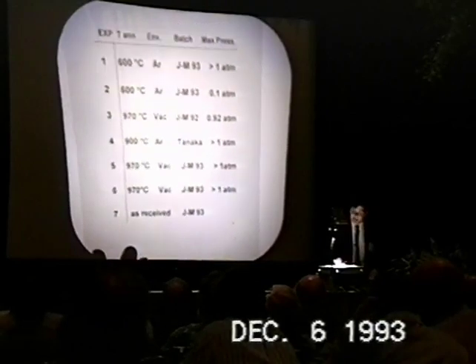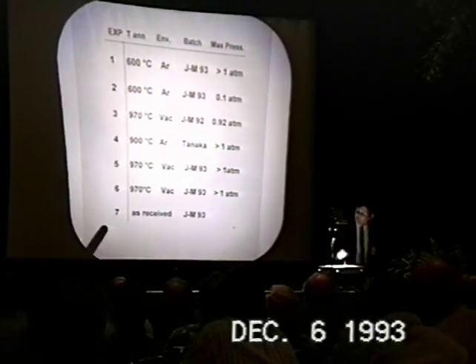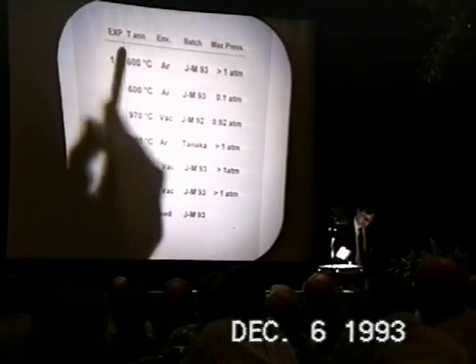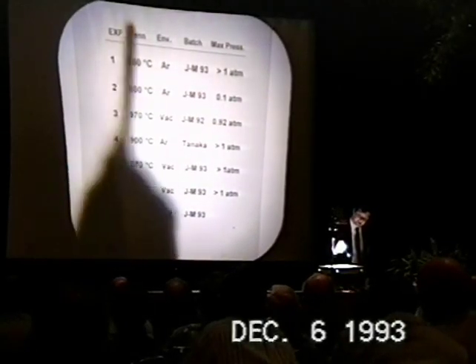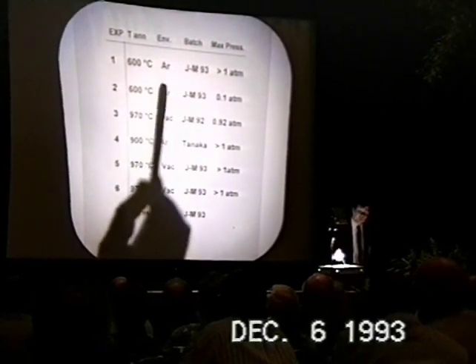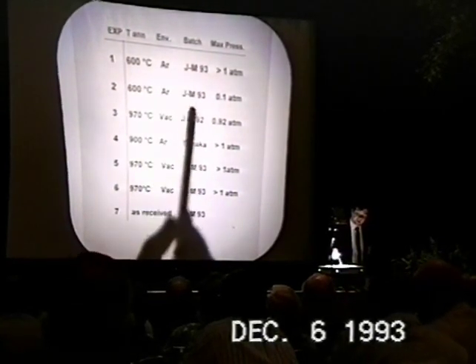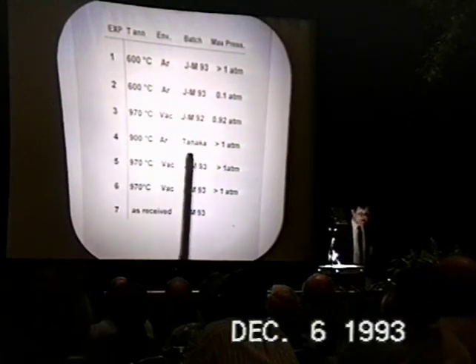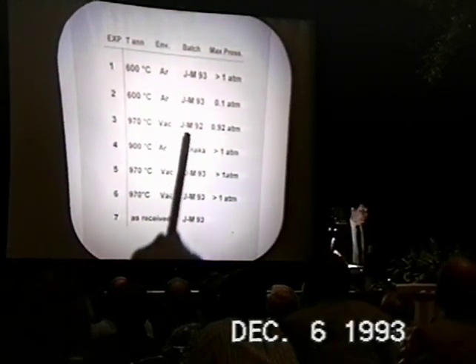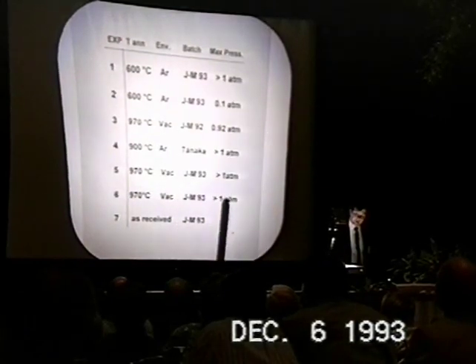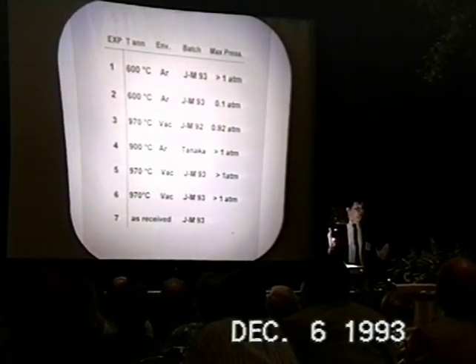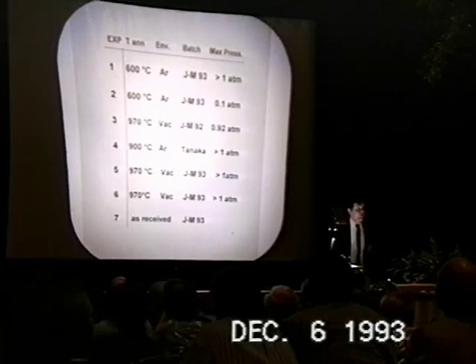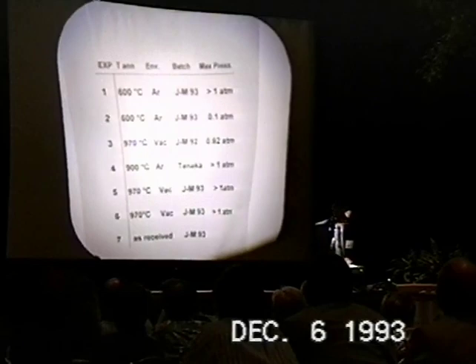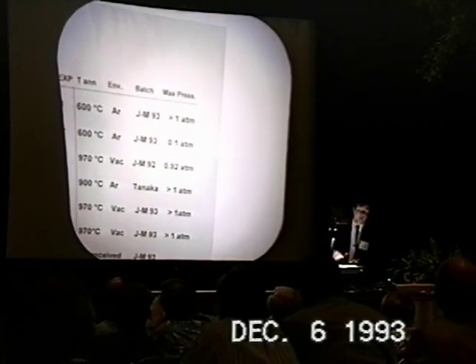Well, just showing you what I mean by database. We have 7 experiments, and we want to see the influence of the annealing environment, the annealing in argon atmosphere or in vacuum, the different batches, the Johnson Matthey, the Tanaka, the old batches that are here, and then the maximum pressure achieved with this membrane technique. And there are other parameters, and before we can understand, we need more data on this.